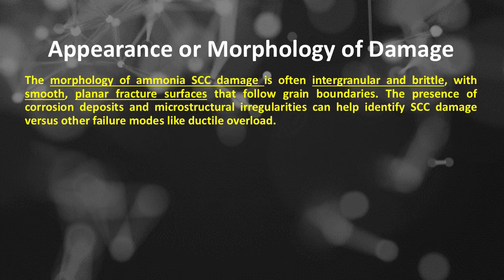The morphology of ammonia SCC damage is often intergranular and brittle, with smooth, planar fracture surfaces that follow grain boundaries. The presence of corrosion deposits and microstructural irregularities can help identify SCC damage versus other failure modes like ductile overload.